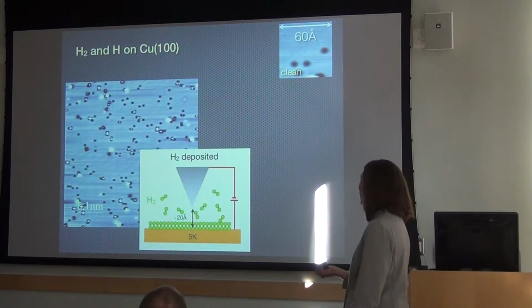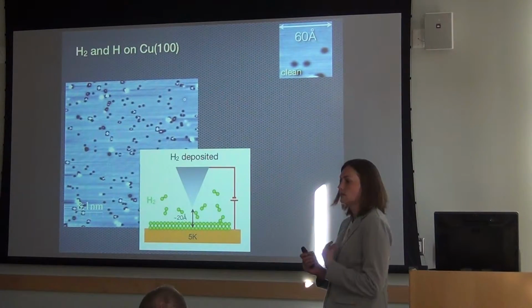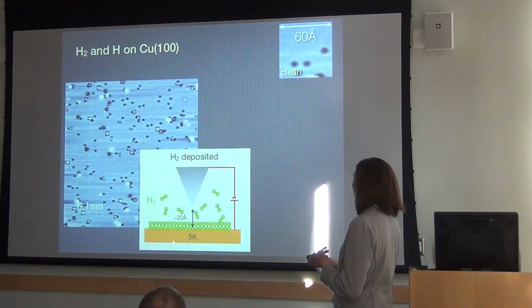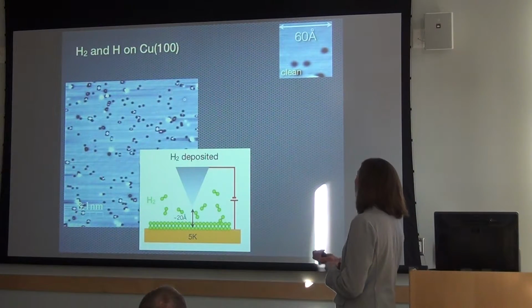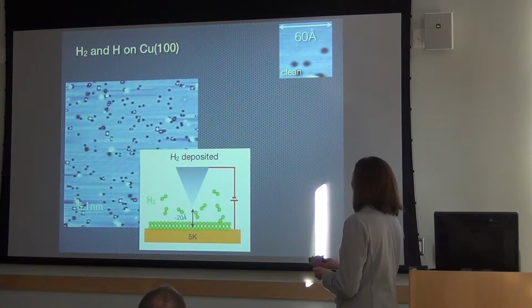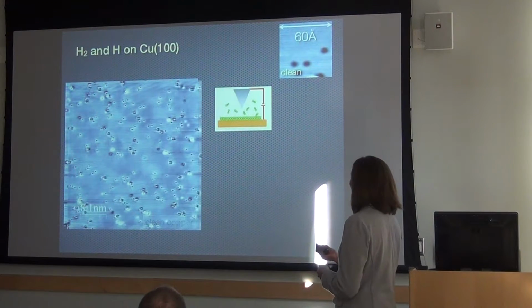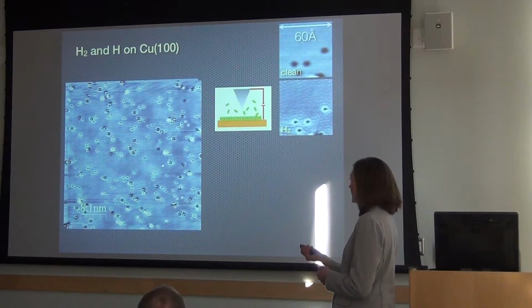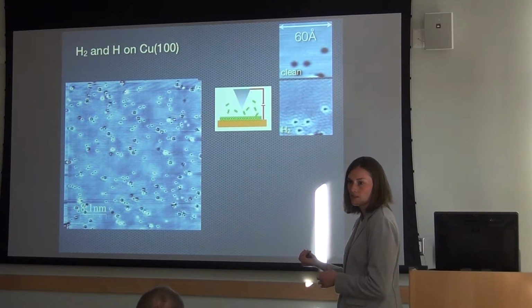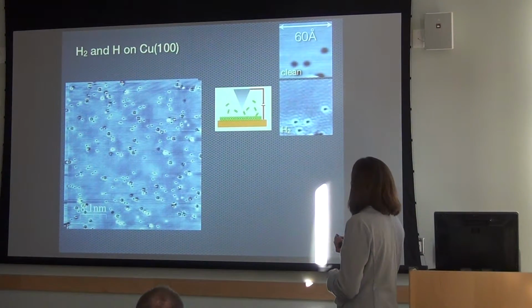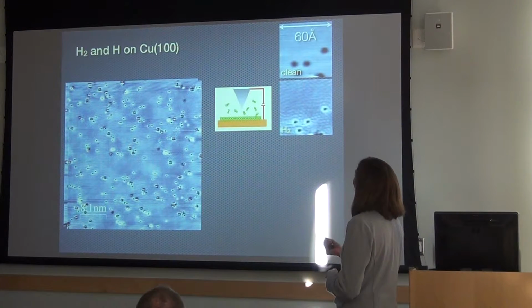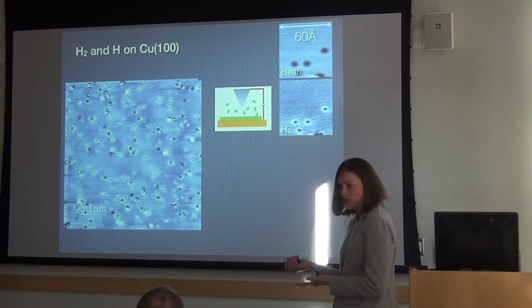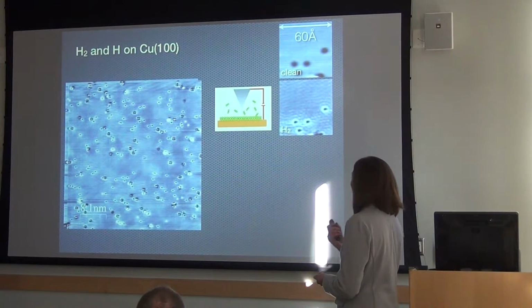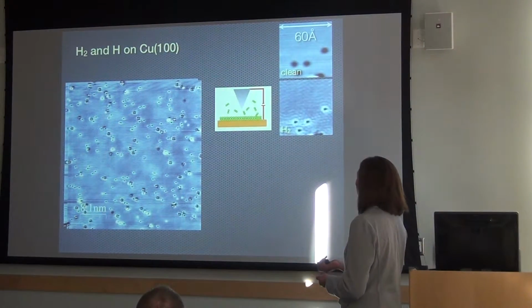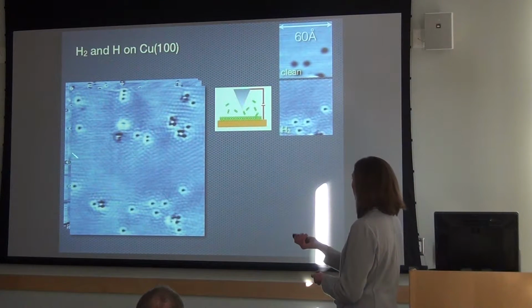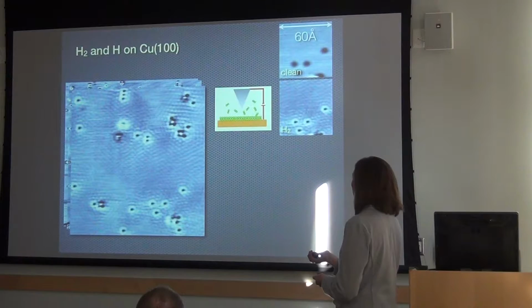So what we did was we dosed molecular hydrogen into the chamber, and the sample is at 5 Kelvin. So the hydrogen adsorbs in a sort of pseudo-organized way on the surface, and you can actually see the close-packed lattice that it makes. And then we needed atomic hydrogen, not molecular hydrogen. So we decided to try to create atomic hydrogen using, here's a zoomed-in view of this nice close-packed structure that you can image.